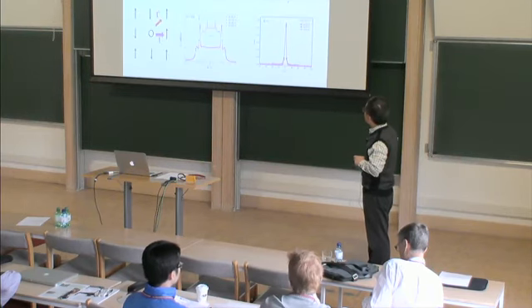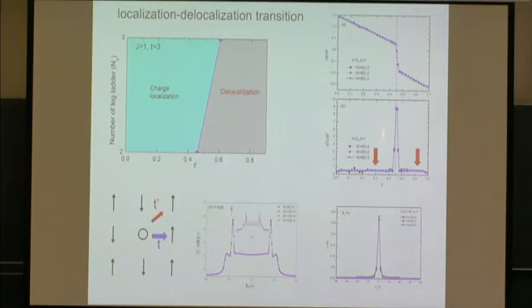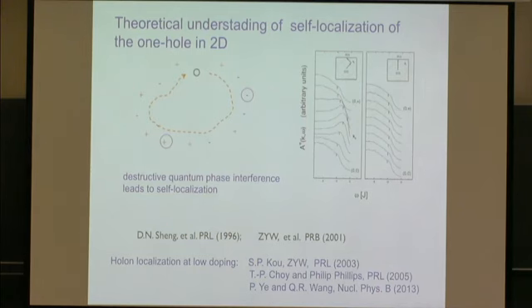So the transition here, you just look at this, the first derivative of energy, the second derivative we repeat here, separate these two regimes, and on these two sides you see again a different scaling of the momentum distribution, for a localized distribution versus a very itinerant quasi-hole. And this is for the ladder case.